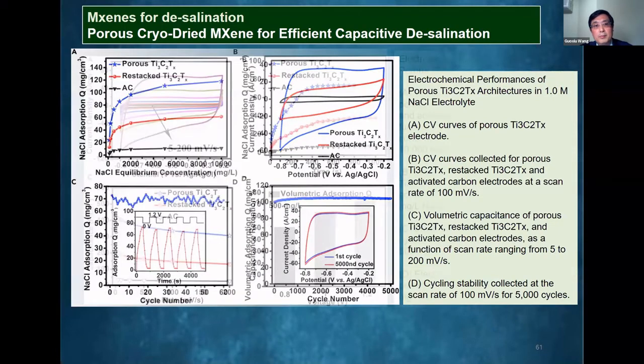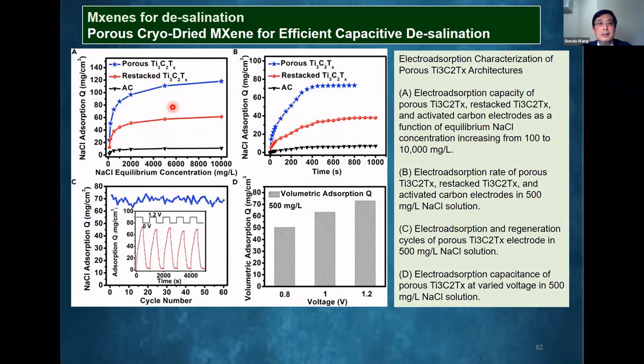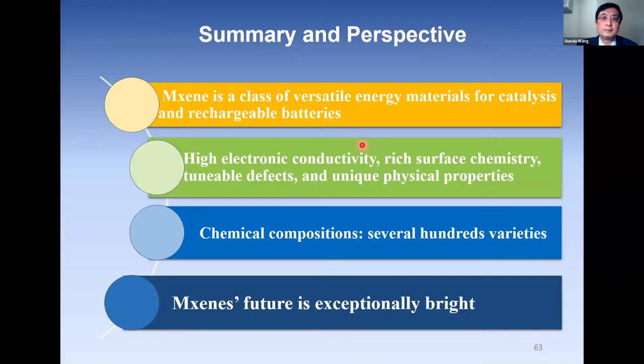And then we applied the porous MXene and also restacked MXene and activated carbon for capacitive desalination. You can see the porous MXene can achieve almost 10 times higher sodium chloride adsorption capacity than the commercial activated carbon. So therefore, I think MXene is a very promising electrode material for capacitive desalination.